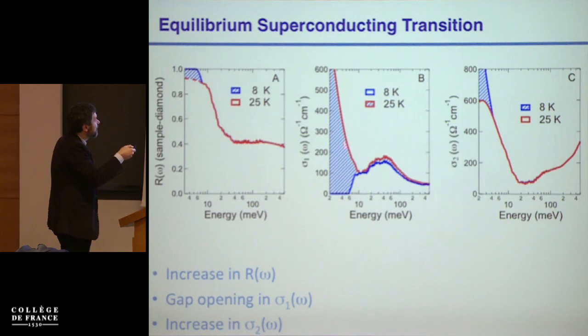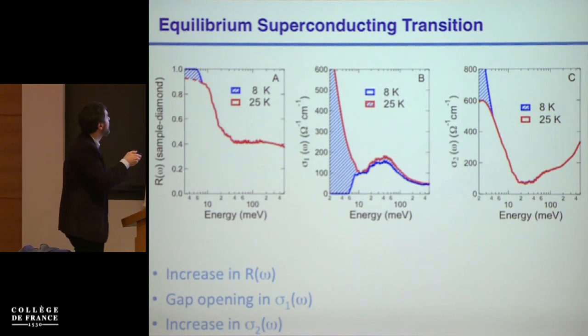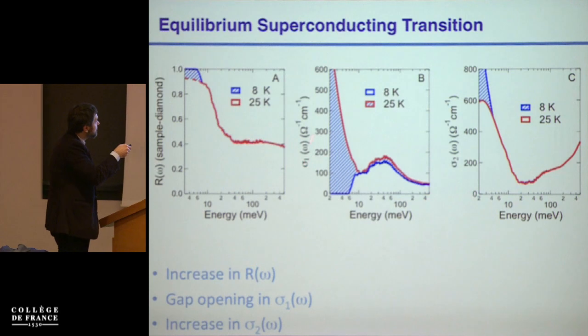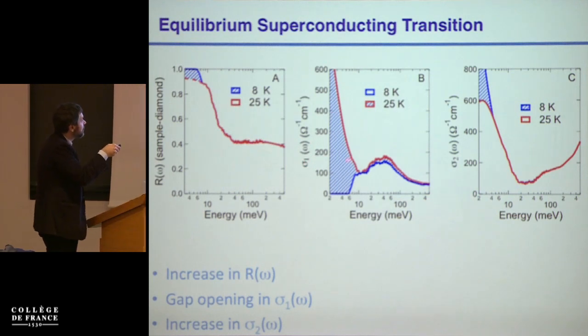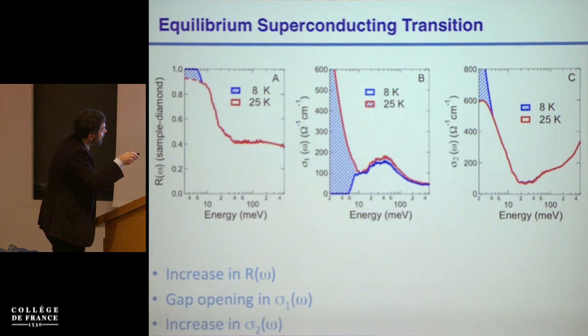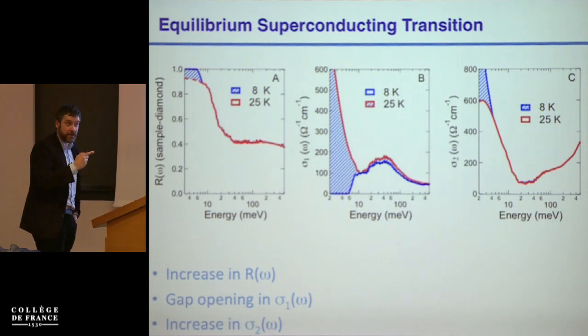Again, the red curve is the normal state conductivity, where the real part of the conductivity has this Drude feature and this polaronic peak. Whereas below Tc, one finds the superconducting gap opening very clearly below 6 meV. And more importantly, or as importantly, a divergent imaginary part of the conductivity, which is indicative of a delta function at zero frequency in the real part of the conductivity.